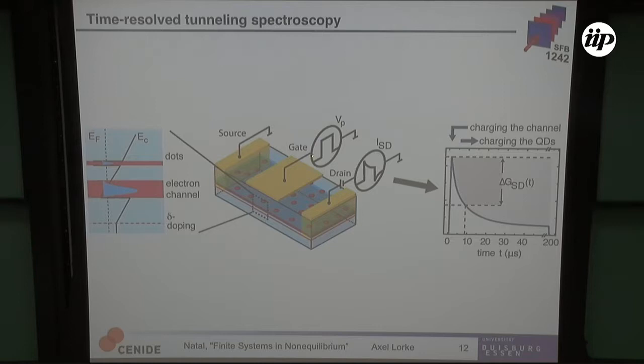So what happens now when you apply a positive pulse to the gate? The same as in every transistor, you increase the carrier density in the channel and the conductivity or the current will jump up. But then, because at the same time you are bringing the quantum states of the quantum dots below the Fermi energy, electrons will tunnel through the tunneling barrier. The extended states here will tunnel into the dots where they become localized states. And this way, the conductivity will go down. So we can, in real time, observe how the tunneling of all these electrons in this layer into the quantum dot takes place.